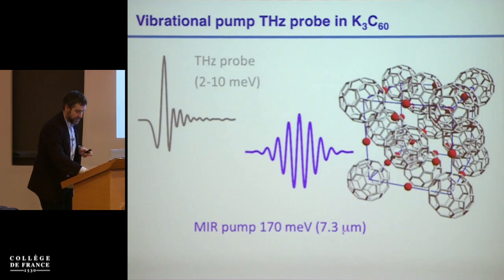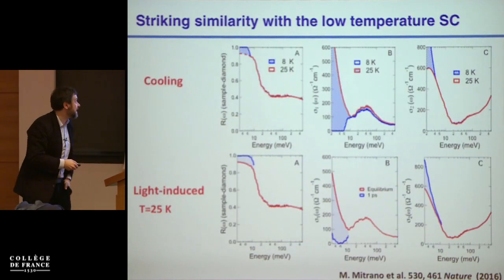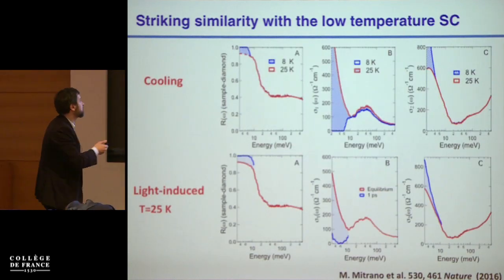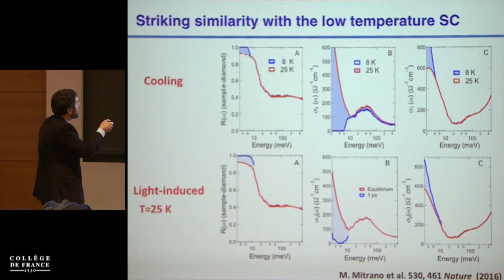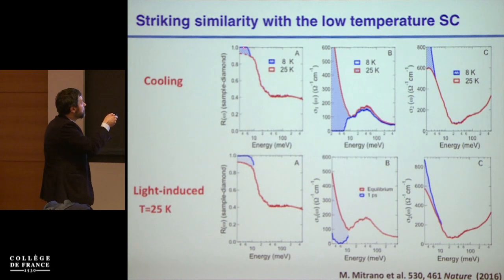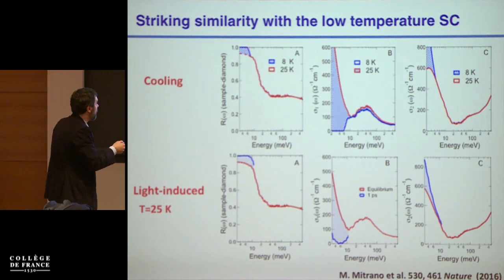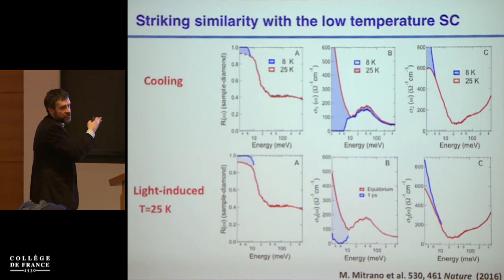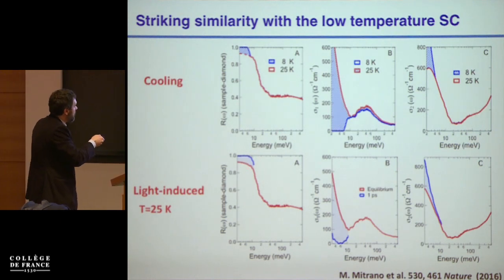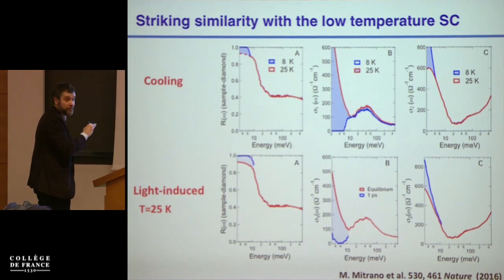And this is really a very satisfying observation, at least as far as I'm concerned, one in which one shows that at 25 Kelvin, one can take the red curve, cool it below Tc to 8 Kelvin, open the gap and give me the divergence. Or one can turn off the fridge and excite the phonon, and one observes the formation of a gap that looks quite similar to the one we observed, only up to a value which is at least, say, 2 times bigger than the equilibrium gap.